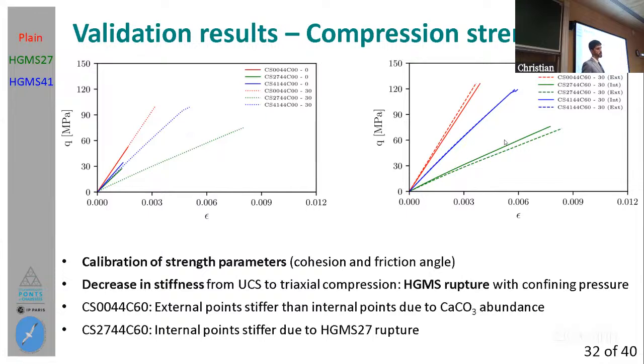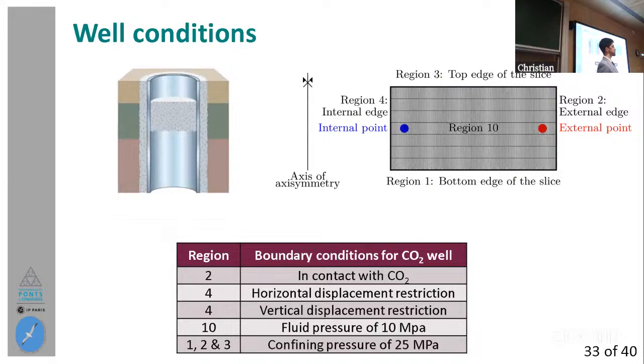If we now go to the other extreme, which is this one, we will see the contrary effect. And the problem here is that we are having a coupled effect of both the precipitation of calcium carbonate, but also a larger extent of the rupture of the spheres. So here, let's say that the rupture of the sphere is winning. Then here in the middle, with the stronger spheres, we have something in the middle. Not winning the calcium carbonate precipitation, not winning the broken spheres. Neither. So with this, I have validated the results that I have obtained in my laboratory tests.